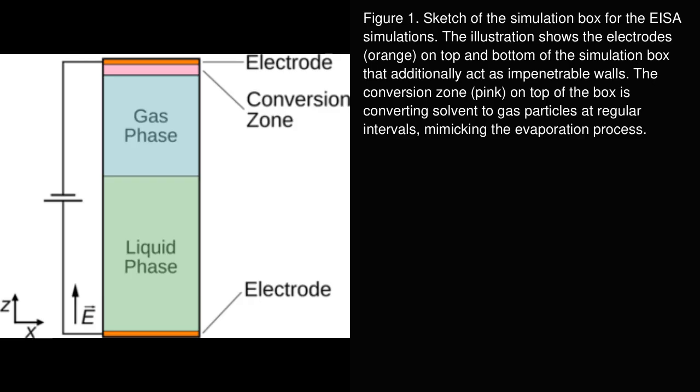Periodic boundary conditions in the lateral directions ensure a representative thin film environment without edge effects. This simulation geometry allows the study of how the applied electric field and solvent evaporation dynamically influence the morphology of the diblock copolymer film, including domain alignment and growth kinetics. The authors interpret this setup as enabling the investigation of the dielectrophoretic aligning effect, where interfaces between domains of different permittivity orient along the electric field vector, lowering the system free energy. Overall, Figure 1 establishes the framework for the subsequent detailed simulations and analysis presented in the paper.